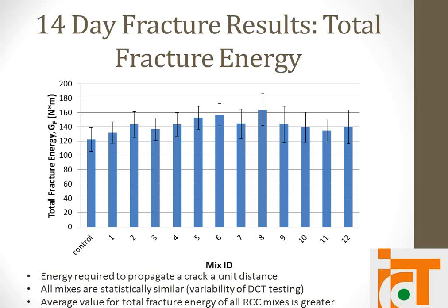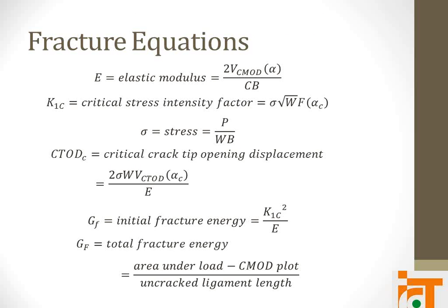Does that cost include labor and equipment? Just total cost, yeah. You say overall that it's very sensitive to the moisture content. With that in mind, all of your mixes use dolomite. Would other aggregate sources change the sensitivity of the strength values considerably, or is it all based on your Proctor optimal moisture? I haven't seen anything in the literature about how aggregate types affect moisture sensitivity, but in general, it is pretty sensitive. There's an optimum, and it falls away pretty fast on either side. Along those lines, conventional concrete mix design is by the SSD method, or surface saturated dry. Is that the same method here? RCC is based on the oven dry weights. So absorption would matter. That's what I was wondering.